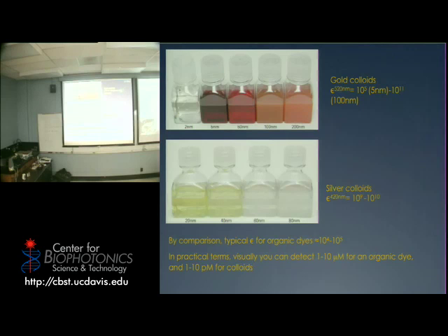These guys go to 10 to the 11. So what it means to you is that in terms of concentration, if 1 micromolar is visually pretty much the limit for a normal chromophore, these guys you can go down to about 1 picomolar. In actuality, you can go down even more than that. You can start seeing why they are important, because if you can somehow couple them with something that you can detect analytically, you can see almost single molecules.